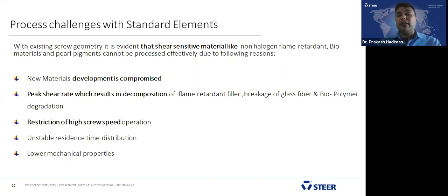And the peak shear rate will decompose flame retardant materials like halogen and non-halogen flame retardants, and biopolymers. The biopolymer starts degrading and forms black specks. There is also a restriction on higher screw speed; many processors start running at 600 RPM because of peak shear, and unstable residence time distribution. There's no control on the residence time distribution, and shear rate is not uniform when using standard technology.